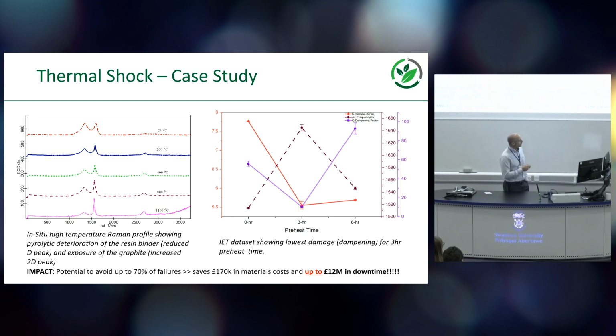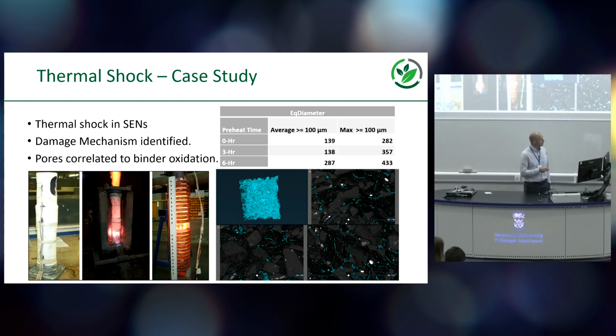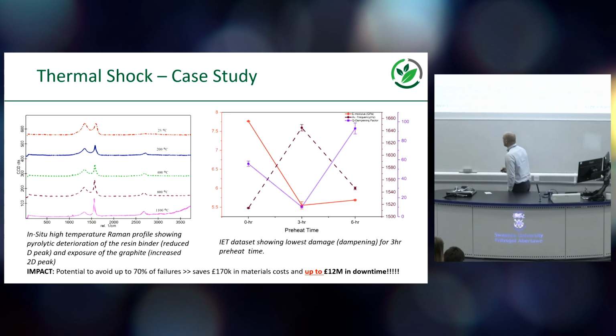And we also did excitation, so basically ultrasonic testing of these as well, to look at where we got the maximum level of damping through the preheat cycle. And where you have the maximum level of damping, you've got the lowest level of damage or crack formation. So you're basically able to use that to monitor the crack formation inside the material. And that enabled us to basically optimize the preheat time, understand why it was optimized as a function of the degradation of the actual components of the system, and correlate that to what we were seeing non-destructively through X-ray CT to make a recommendation on what you can do on that, which has the potential to significantly improve the productivity of the process. Because if you lose a SEN in the middle of a cast, Matthew would tell you that's a big problem.